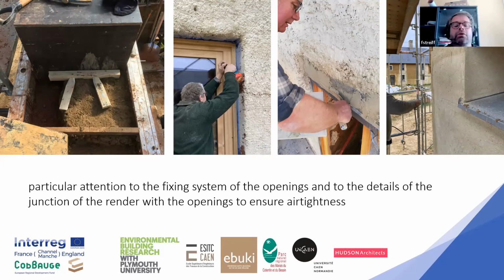So that kind of plastic mesh implemented in lime plaster, in the internal or external lime or earth plaster, works pretty well. And we made some tests, some blower door tests, to see if we managed to achieve the rule regarding that in the thermal regulation, and just by plastering the wall, just filling the small cracks or small gaps in the cob wall, we managed to pass the regulation quite easily.